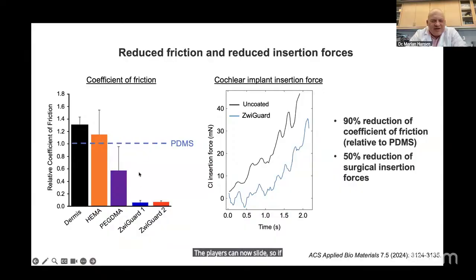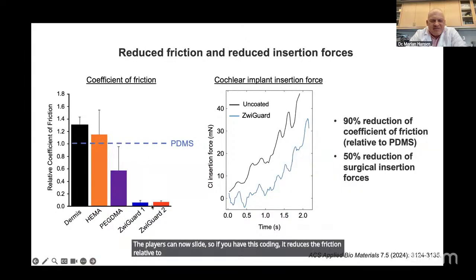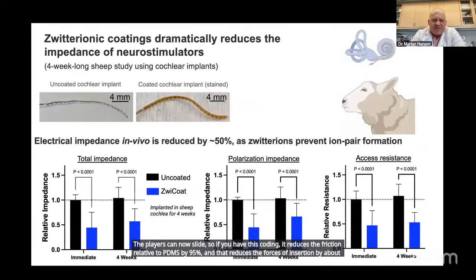The other thing it does is it holds a water layer, so it makes things really slick, just like if you have a football field and you put water on it. The players can now slide. So if you have this coating, it reduces the friction relative to PDMS by 90%, and that reduces the forces of insertion by about 50%.